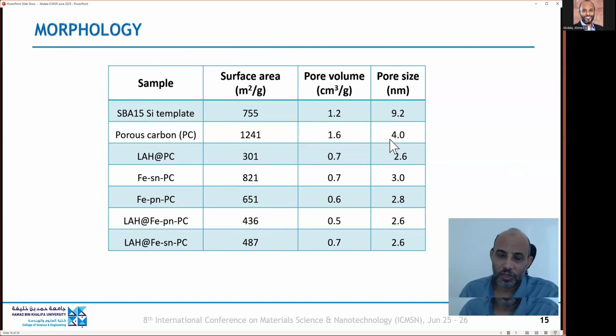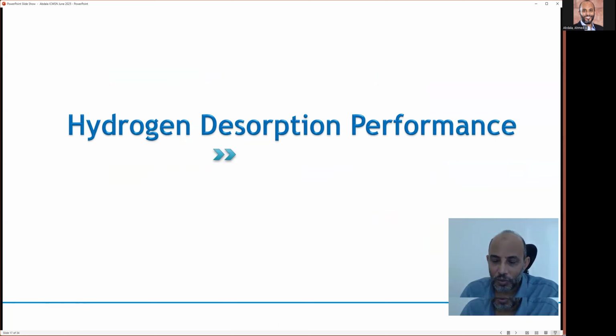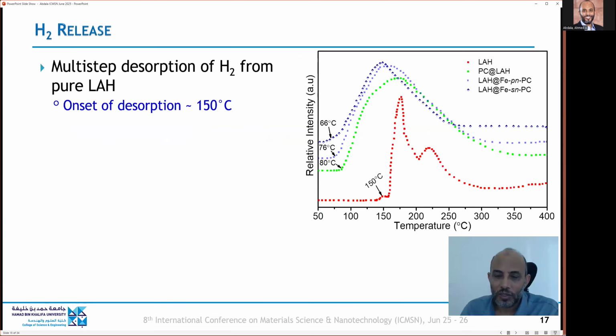Pore size, you can see mostly on the porous structures, basically. So the metal hydride pore sizes didn't significantly change, but their surface area is improved. So now we'll look at the performance of the catalyzed metal hydride. So first we look at the hydrogen release, using temperature programmed desorption.